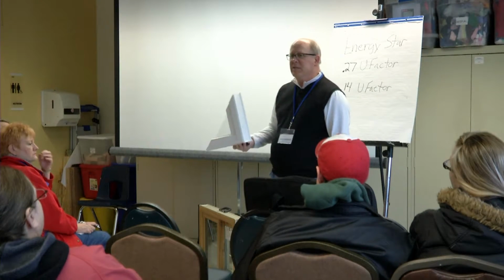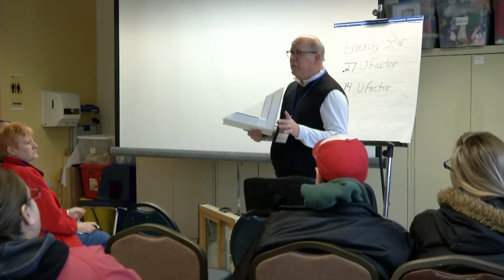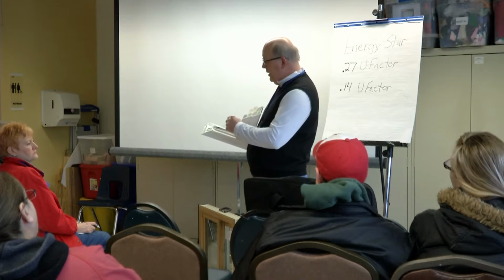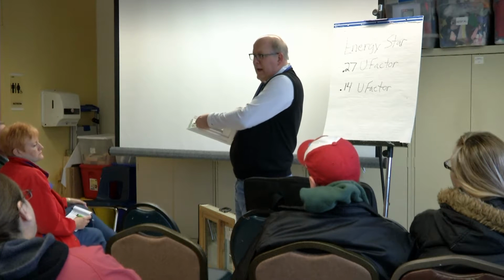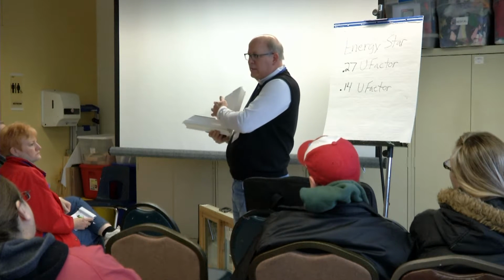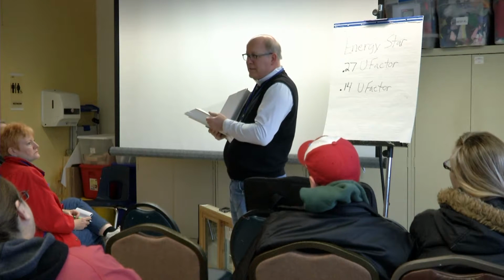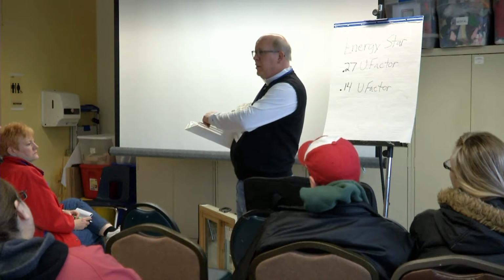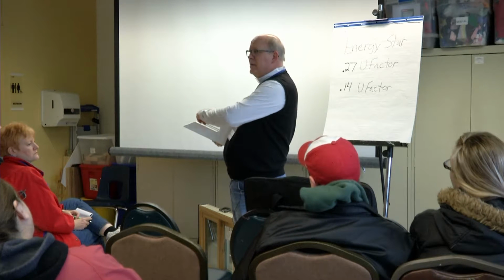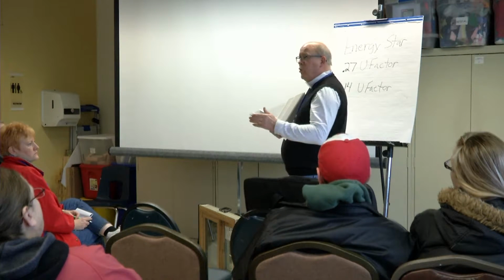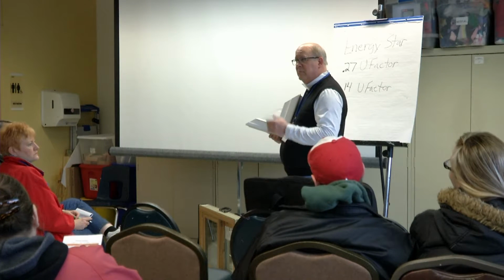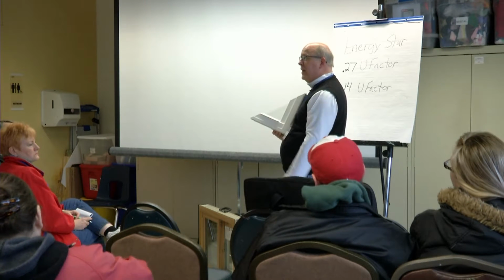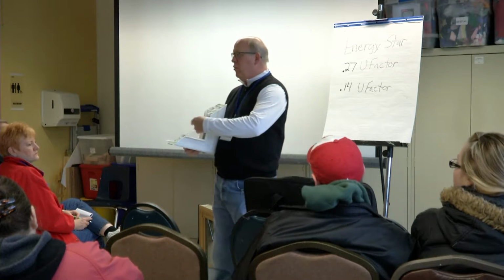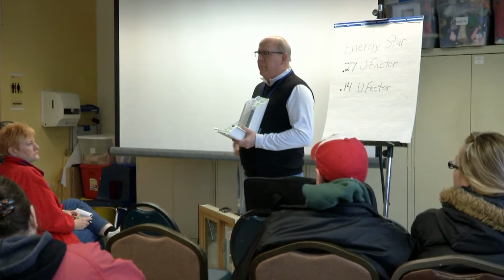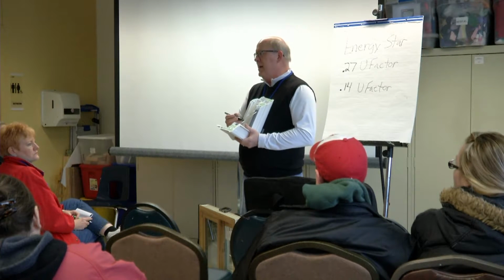Okay? In Minnesota, the absolute best place to have your low emissivity coatings would be, they always put them on the inside piece. They don't want it exposed where it can get scratched or messed up in any way. They'll put it in here, but the best place for it would be on the inside of the inside pane, because we have many more heating days than we have cooling days. So we'd want the infrared heat from the house reflected back right away before it can get in here and warm this up and re-radiate it to the outside. But most glass companies with 2 panes always put it to the outside.